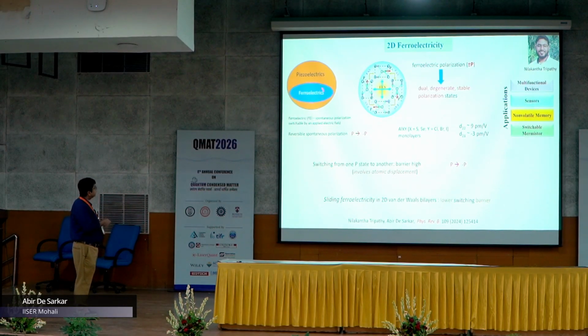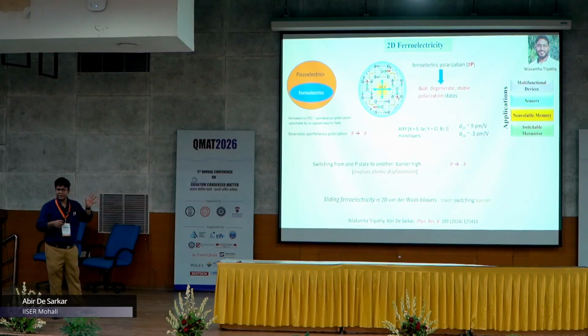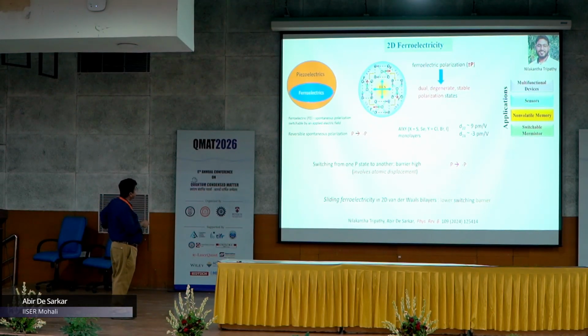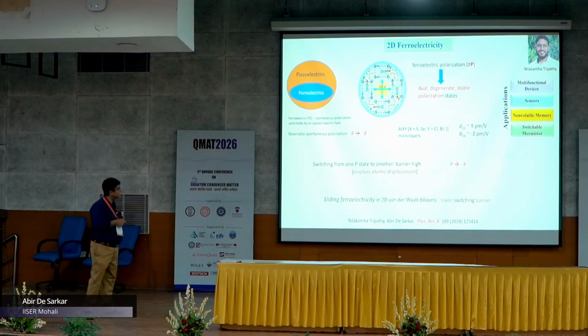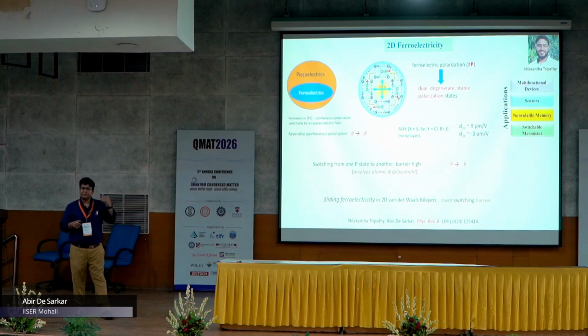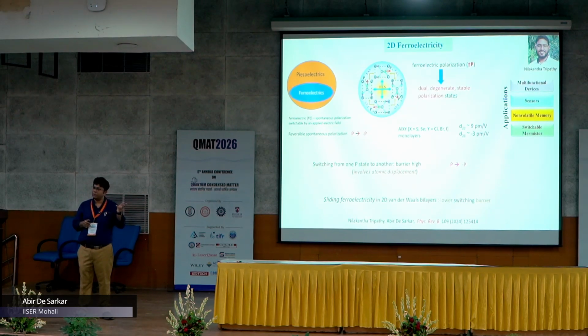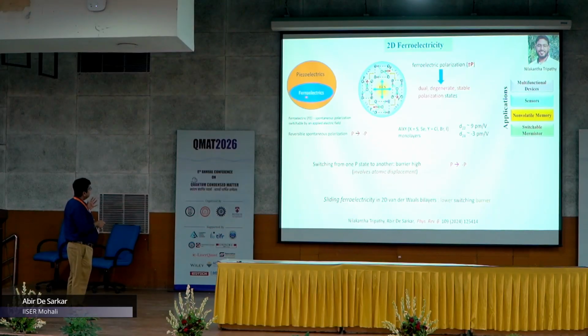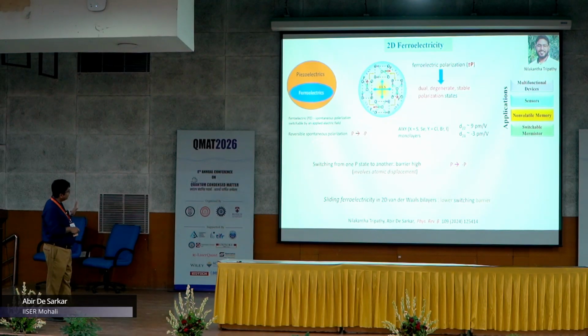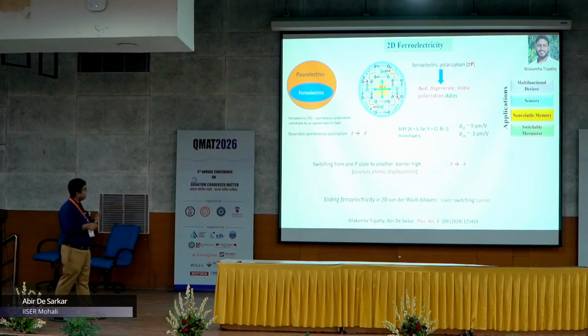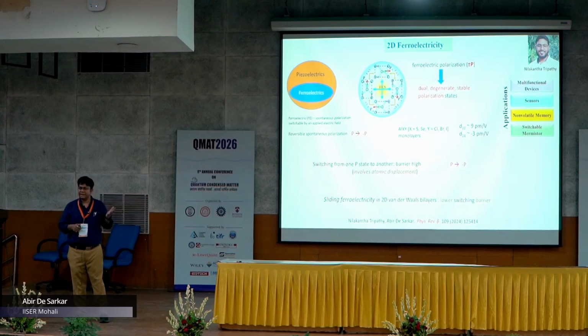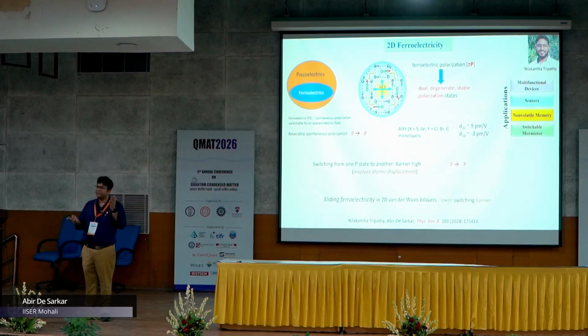And now, it is time to switch gears to ferroelectricity. Ferroelectricity is a subset of piezoelectricity, and ferroelectric materials show a spontaneous polarization, unlike the piezoelectric materials which exhibit polarization under the application of electric field, strain or pressure. In ferroelectric materials, the spontaneous polarization can be switched by the application of an electric field. So, there are two stable states of polarization, P and minus P. By the application of electric field, one can switch the direction of polarization from plus P to minus P. These are dual degenerate and stable polarization states in a ferroelectric material, which can be switched by the application of an electric field.